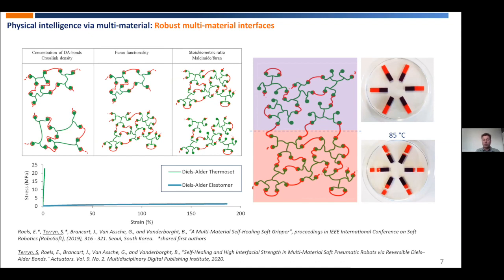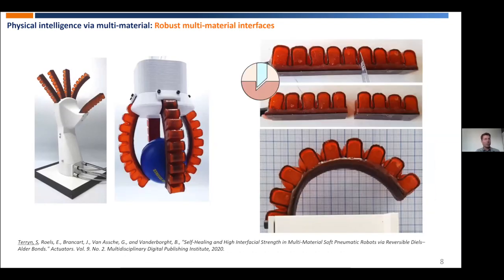And the result is that we have a very strong multi-material interface, which we can use in soft robots. And this is what we did. So the robotic systems that you can see there are composed of multiple materials. But the interface is very strong, very robust, so the part will not break there.